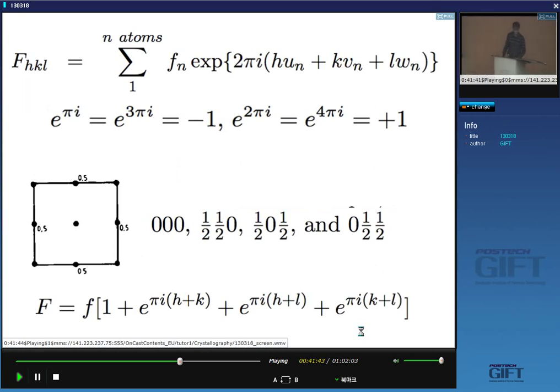Now, supposing that I asked you, do we get a 1-2-3 reflection? Then it's hard to look at the shape of the unit cell and decide that, right? It's too difficult. Or a 1-2-5 reflection, will that appear in cubic F? So the basic principle is that if there are scattering centers inside your unit cell which scatter out of phase, then you will not get that reflection. And the way you can express that mathematically is to add up the waves coming from different regions of the unit cell. Right? So this is called a structure factor for a particular plane HKL.